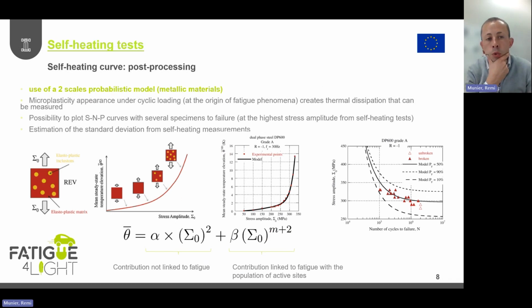Then for a second approach, we can use a probabilistic model, because as we know, fatigue is a dispersive phenomenon. Having information about the endurance limit is good, but we also need an estimation of the standard deviation according to fatigue tests. So for metallic materials, we developed a two-scale probabilistic model representing a progressive appearance of microplasticity. And then we can completely describe a self-heating curve for low regimes of temperature and then for high regimes.